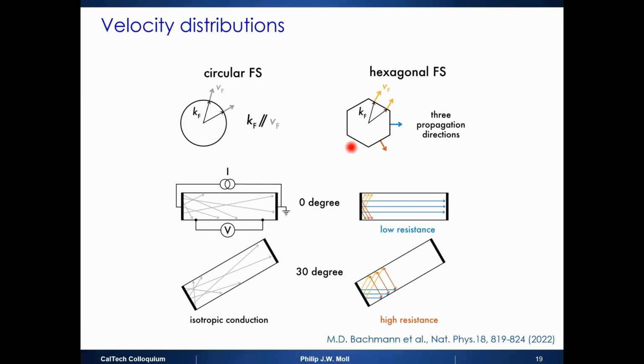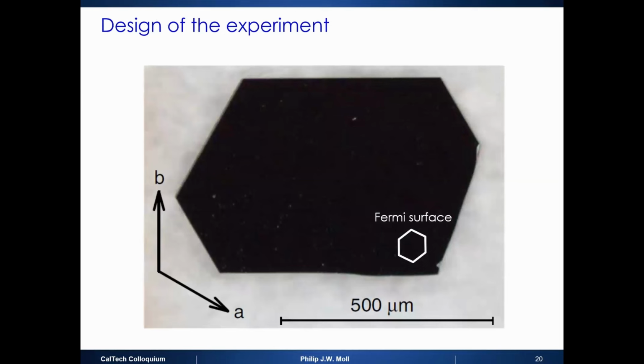In the hexagon, it's very different. If you go in one direction where it's, let's say, rotated like this, you have this beam of massive divergent density of states that essentially moves along this thing and never sees your boundaries. So there will be no boundary scattering. If you off-rotate it like this, there's no such state, and the electron just bounces between the different sides of this structure, okay? So you would actually expect an anisotropy in the ballistic conduction that is forbidden by group symmetry in a diffusive case.